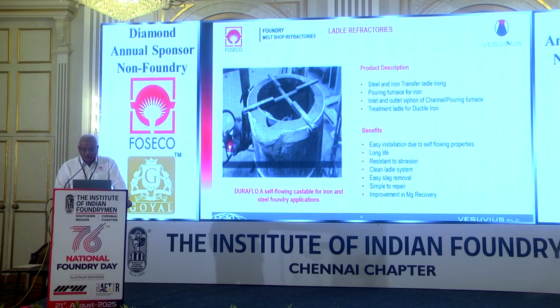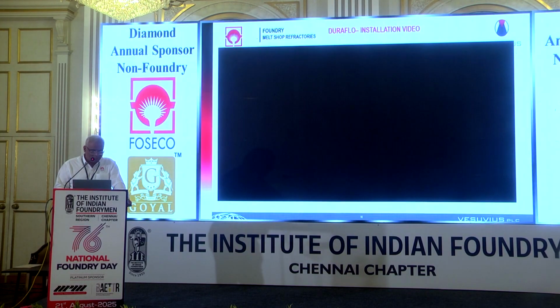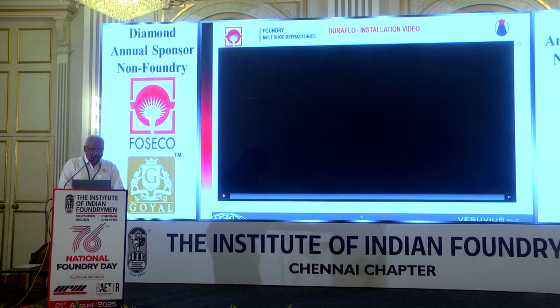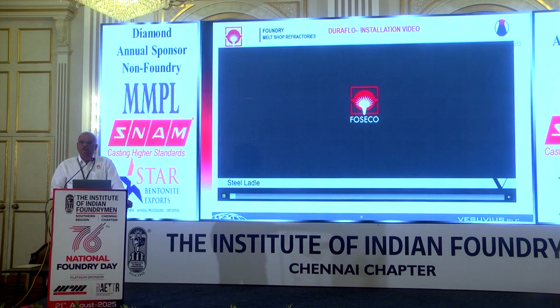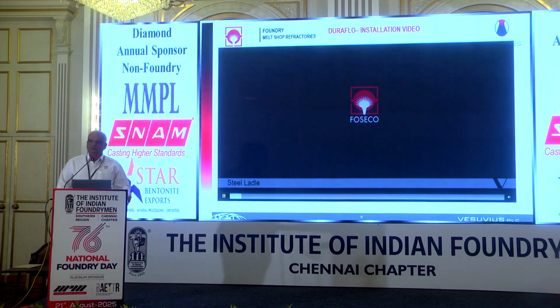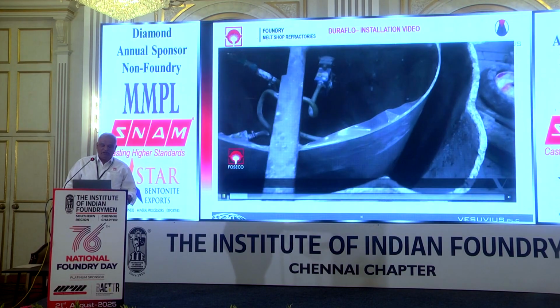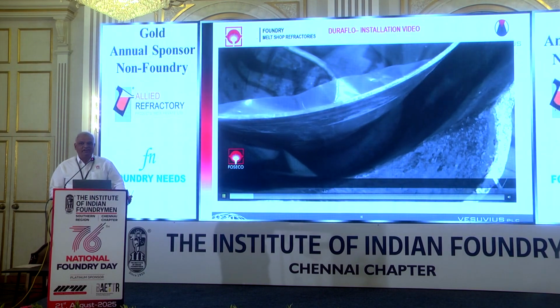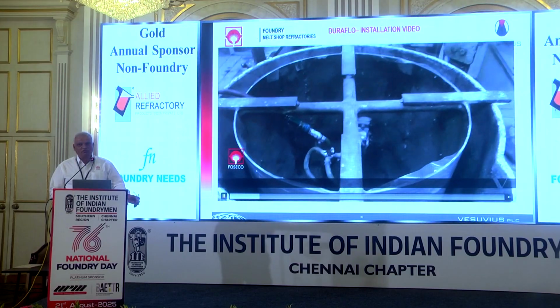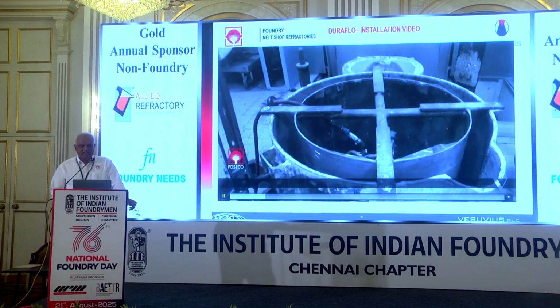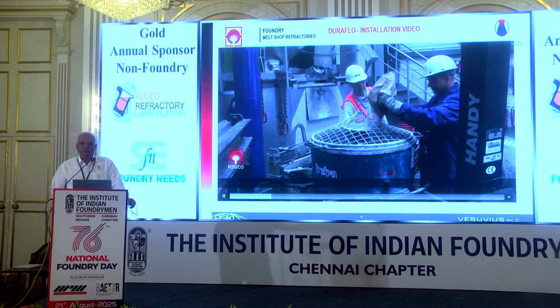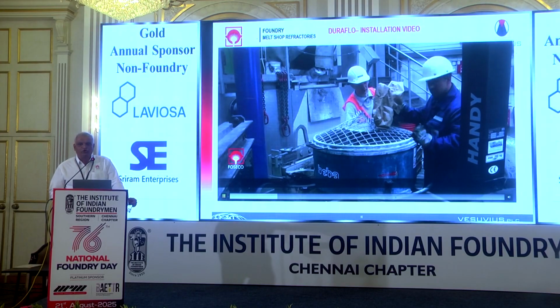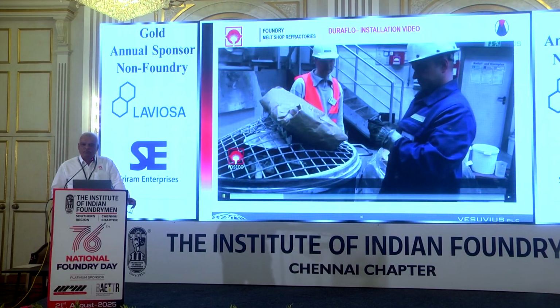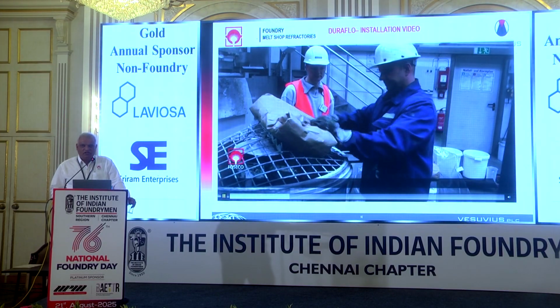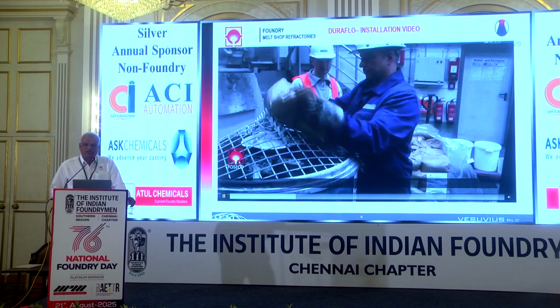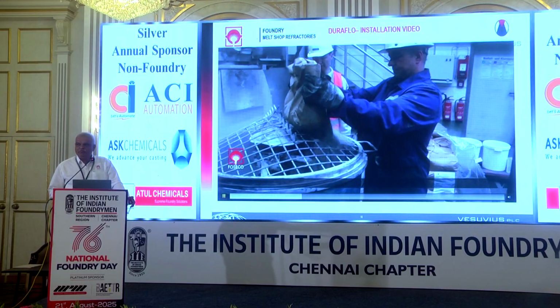I will just run one video of how to install these LC castables. These can be used for steel as well as iron foundry ladles. It can be used for treatment ladles also. For this, a former, similar to what we make for the furnace lining, is mandatory. It requires a mixer, because the water addition in this is very low compared to conventional castable, so to get proper mixing we require a mixer. Water addition is around 6 to 8%.